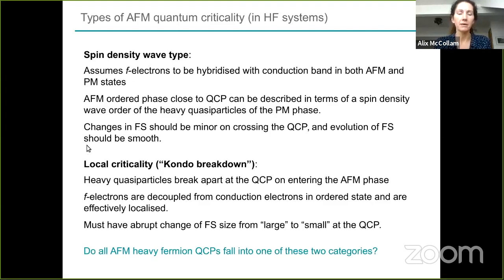Another possibility is a local criticality scenario, or the Kondo breakdown scenario, where when you go from the paramagnetic phase, from the well-developed Kondo state, into the antiferromagnetic phase, the heavy quasiparticles just break apart. So the Kondo singlets don't come apart slowly, they break apart directly, and the f-electron goes from being itinerant, incorporated in the Fermi surface, so hybridized into the conduction band, to being localized, and a small Fermi surface then in the antiferromagnetic state. So in this state, you just have local moments in this antiferromagnetic phase, and the Fermi surface has to change abruptly at the quantum critical point. So when you go from paramagnetic to antiferromagnetic, you have a large to small change of the Fermi surface abruptly. So this is something that you would be able to measure rather straightforwardly.